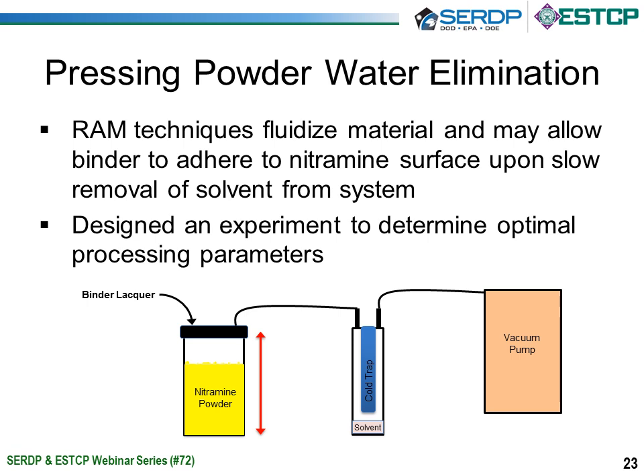Not only that, but through the use of the cold trap, we can collect the solvent and reuse that solvent to make future binder lacquers for future runs. So therefore, there is very minimal, if any, waste associated with this process. We developed a design of experiment to try and determine optimal processing parameters in order to develop the narrow distribution of the granules and the high yield of the granules in this process. Slide 24, please.